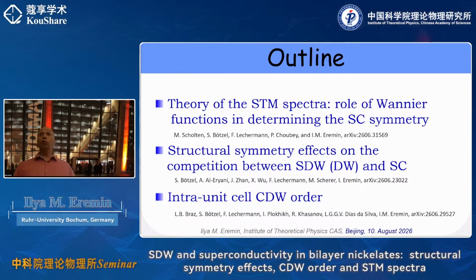And then the other topic is that we were studying the origin of the fact that it's known there are two transitions in the parent phase. There is a magnetic transition, but there is in the resistivity another transition, which is interpreted as a density wave transition, which is not seen in muons. So it means it's probably a purely charge origin of the transition. And furthermore, they show a very different behavior if you apply small pressures. That has been done also by Mirza's group. They saw that the spin density wave transition is going up, and that has now been confirmed also in this study of these AM2M phases. And the charge density wave transition is going down. So that's very unusual, and this is also something we try to understand with Lauro. And I will speak about this at the end.